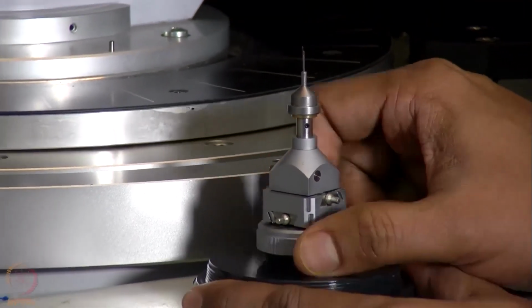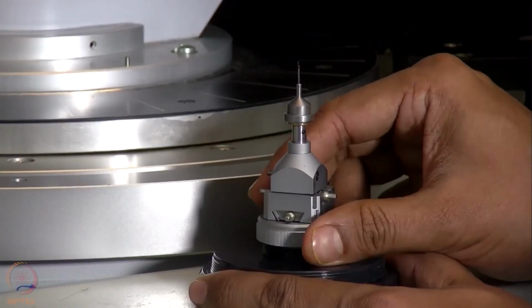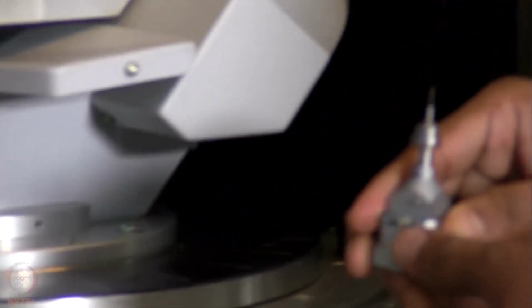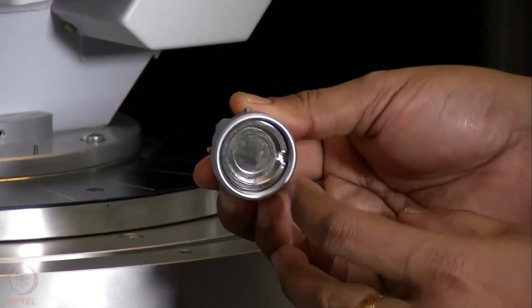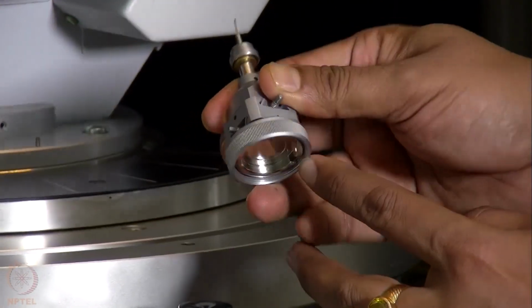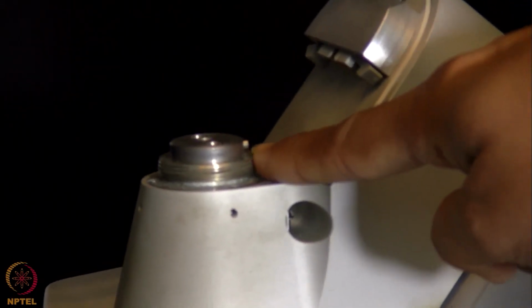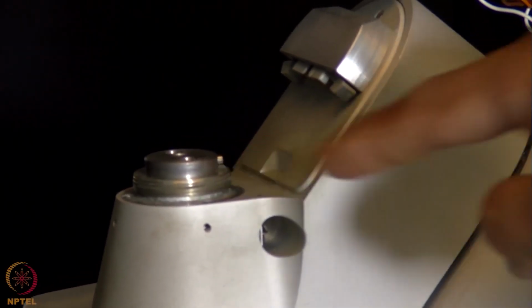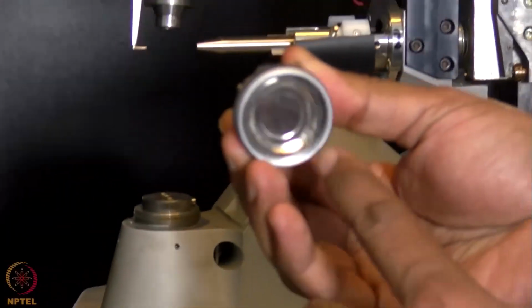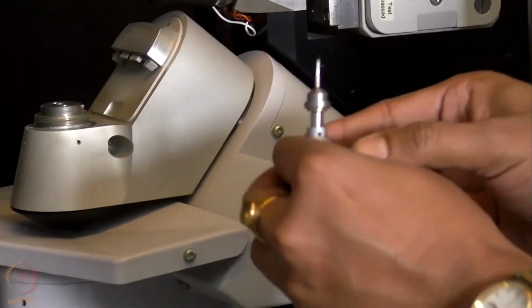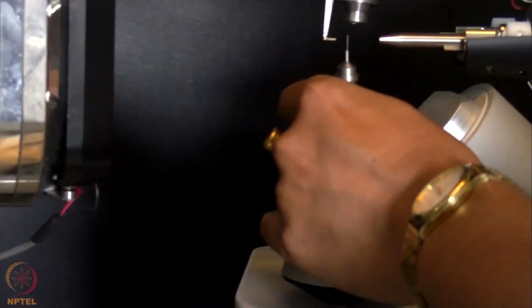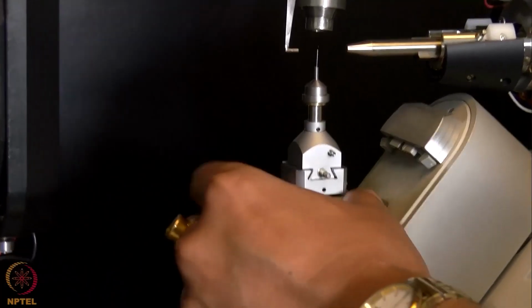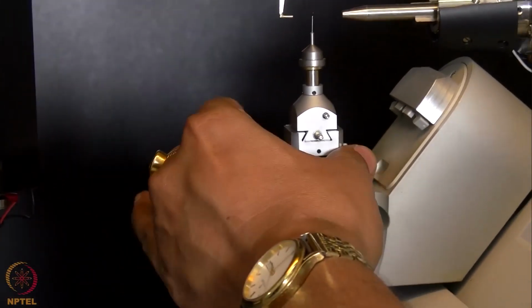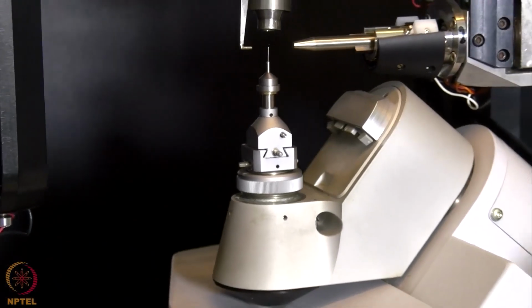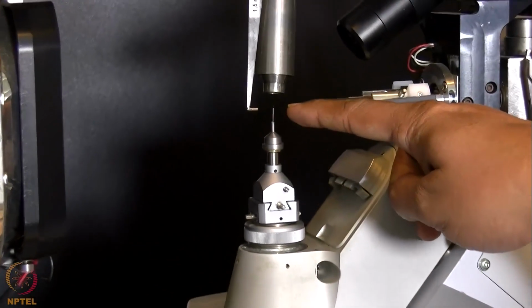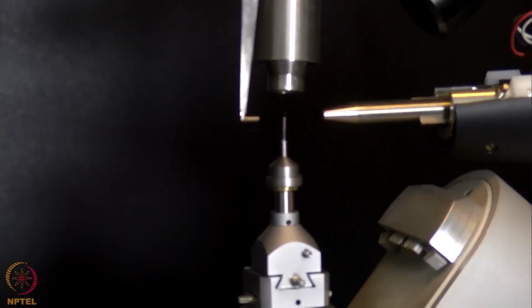So this goniometer head has to go and sit on the goniometer. You can see here at the bottom there is a notch here, and on that goniometer base there is a notch which should go and sit along with this gap here. So that is the locking mechanism which holds the goniometer head on the diffractometer constant. Then we turn the screw and just hand tighten it, and then you can see the crystal is mounted here. It is in front of the beam, and then there is a beam stop.